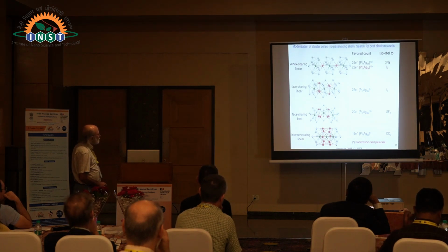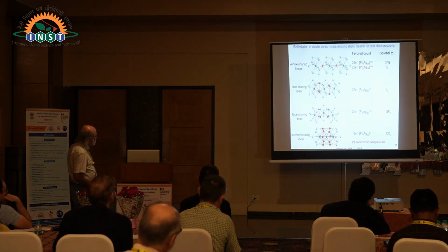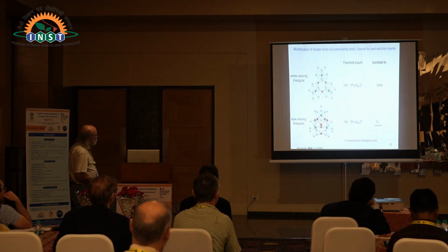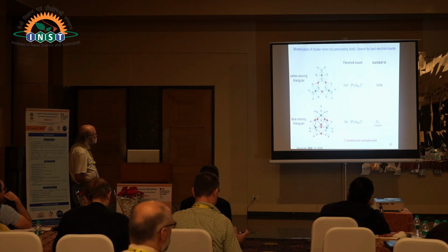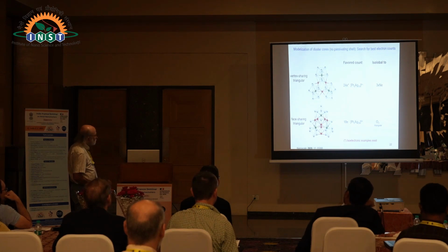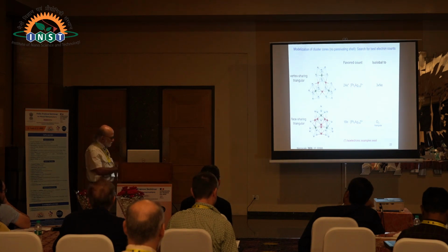More compact, face sharing, linear, 22 electrons. It would correspond to I3 minus. No examples in the literature so far. Face sharing, but bent now, 20 electrons, equivalent to SF2. No, it's a prediction so far. Three interpenetrating icosahedra, 16 electrons, equivalent to CO2, and there is at least one example in the literature. We can make a triangular system, vertex sharing, well, it's 24 electrons. But if it's face sharing, then the favored electron count is 18. It corresponds to the hypothetical high-energy isomer of ozone, triangular O3.